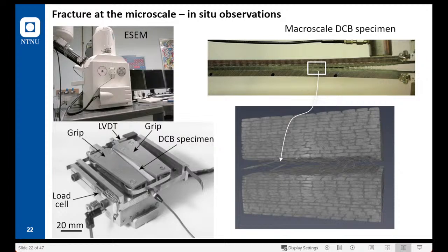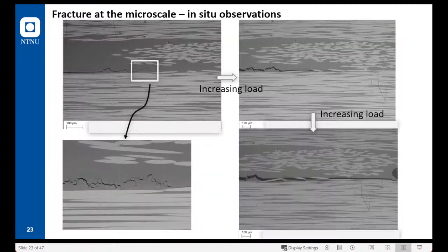These are micro CT images. But if we want to see how the material fails at a micro scale, we perform these micromechanics experiments. And we can see in detail how the crack will grow. Every figure here corresponds to an increasing load. So we can see how the crack growth is affected by the microstructure.